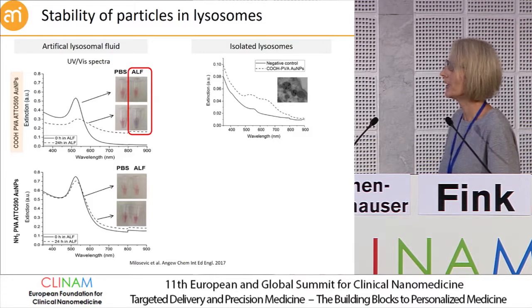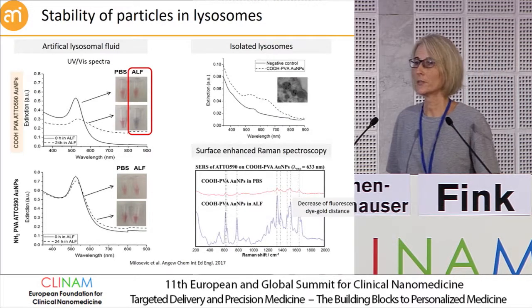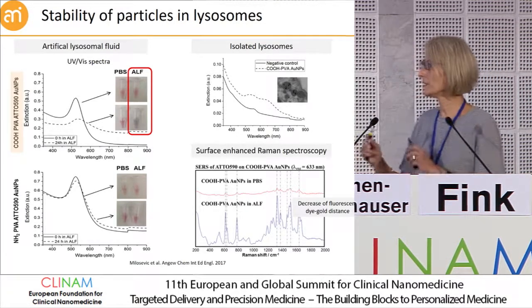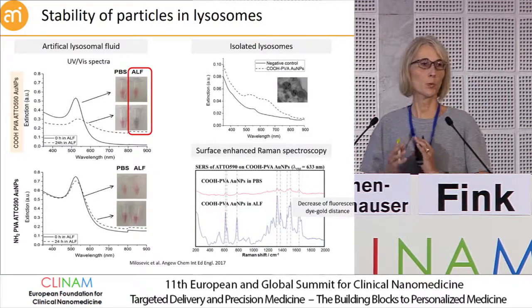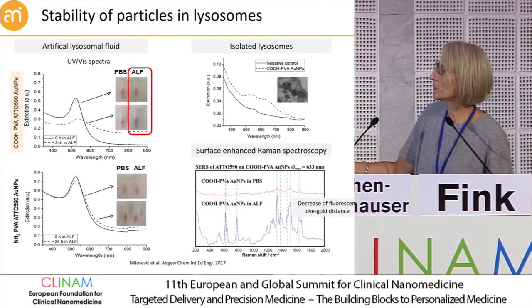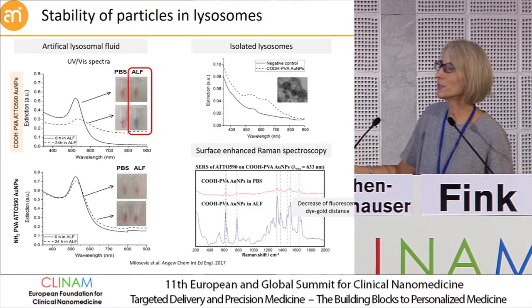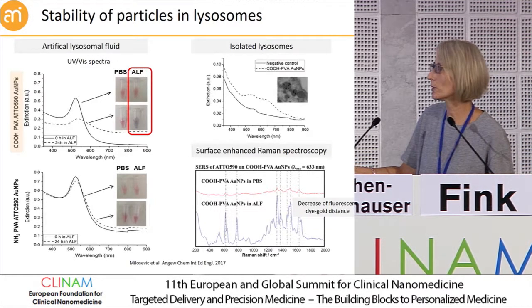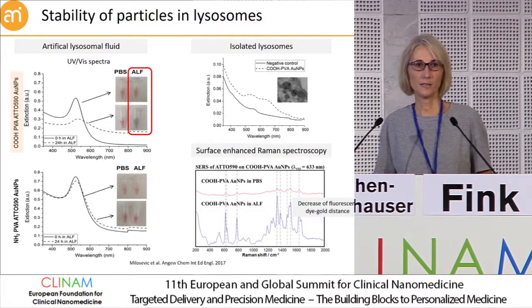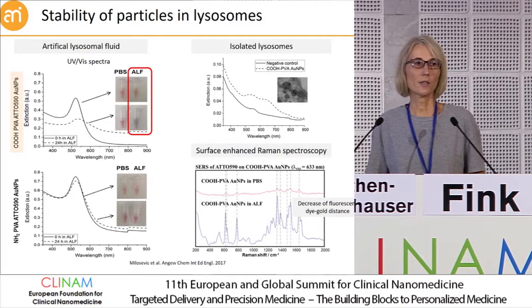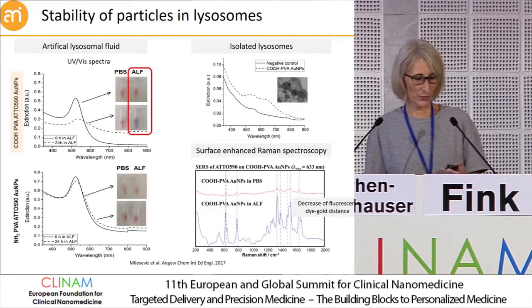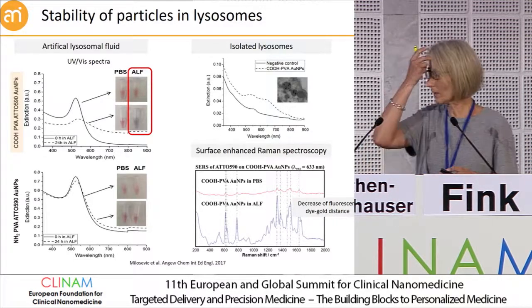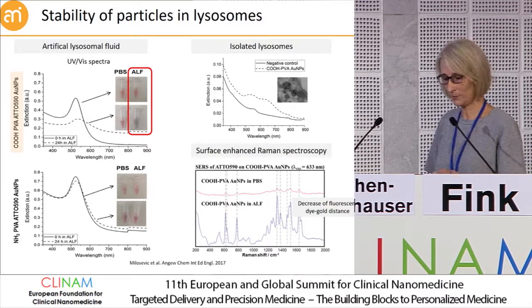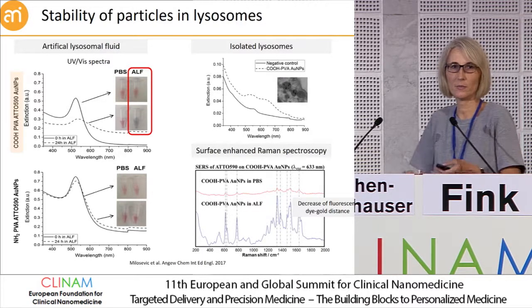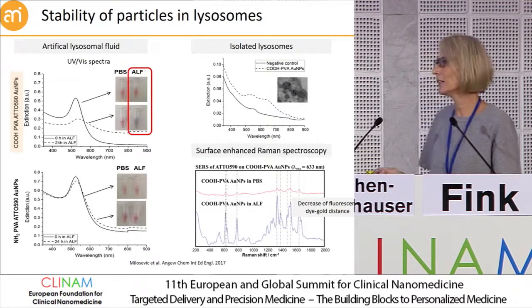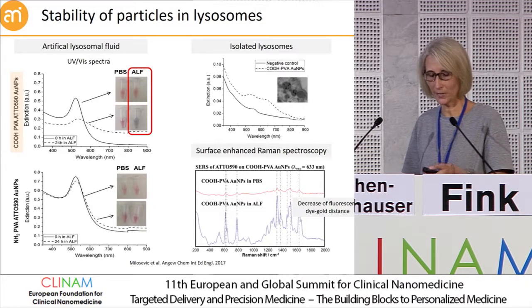charged particles. So by surface-enhanced Raman spectroscopy, we have seen that somehow the polymer was swelling, and this induced a decrease of the distance from the fluorophore to the gold core, which then finally resulted in a quenching. So it was just the environment which has reduced the fluorophore properties, or decreased these fluorescent properties, and we still have particle uptake. So we have to be very careful with all these investigations.